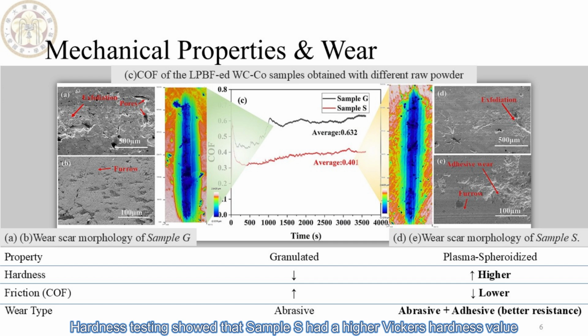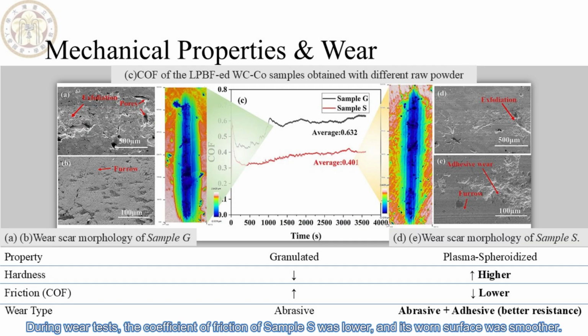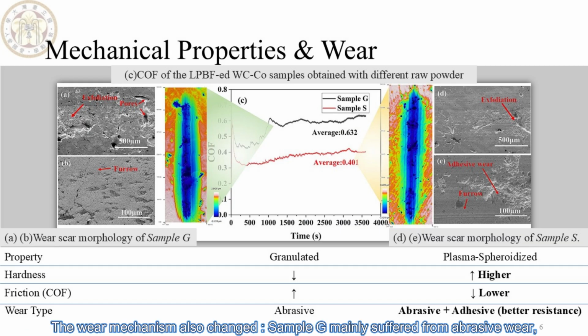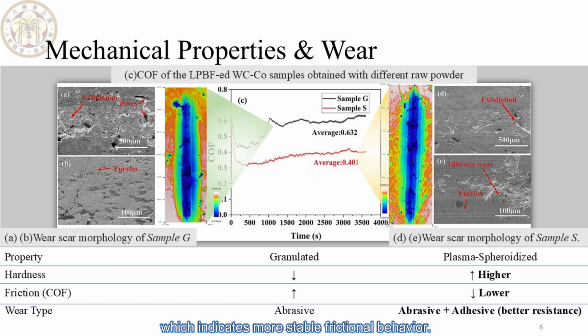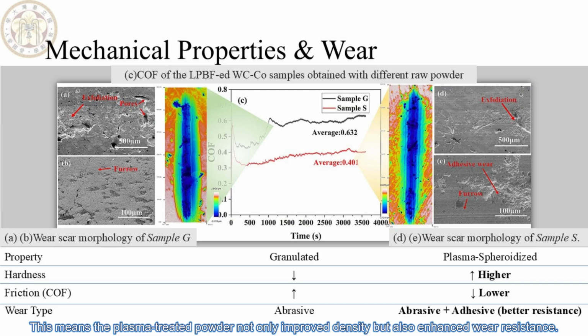Hardness testing showed that sample S had a higher Vickers hardness value due to its finer and more evenly distributed WC grains. During wear tests, the coefficient of friction of sample S was lower, and its worn surface was smoother. The wear mechanism also changed. Sample G mainly suffered from abrasive wear, while sample S showed a combination of abrasive and adhesive wear, which indicates more stable frictional behavior. This means the plasma-treated powder not only improved density but also enhanced wear resistance.